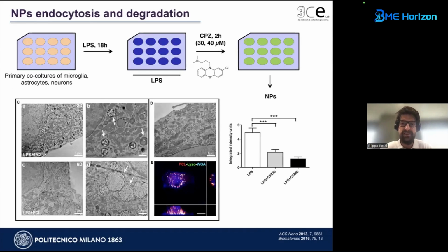So basically, very simply, we introduce an inhibitor of endocytosis called chlorpromazine. We started with primary cultures of microglia, astrocytes, and neurons. We obtained activated cells. Then we added chlorpromazine at different concentrations that can inhibit endocytosis. What you can see from the graph on the bottom right is that by increasing the concentration of chlorpromazine, you decrease the uptake of nanoparticles, but as you can see, not completely. So it means that endocytosis is very important, but it's not the only mechanism. What about the fate within the cells?